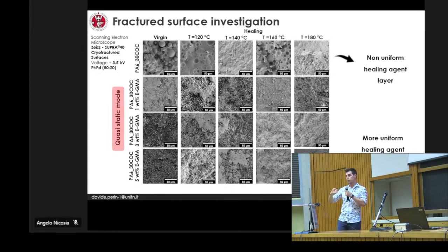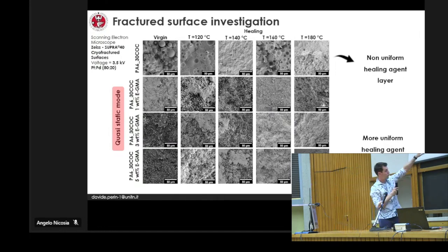When we actually perform the healing process, we increase the temperature. The COC is totally amorphous, so above 100 degrees C, it starts flowing slowly, but it starts flowing. So at 160 degrees C, you are actually giving a lot of energy, so it is able to flow slightly. By keeping the damaged surfaces in contact, you are able to soften the polymer. This polymer will go inside the crack. And here you see,